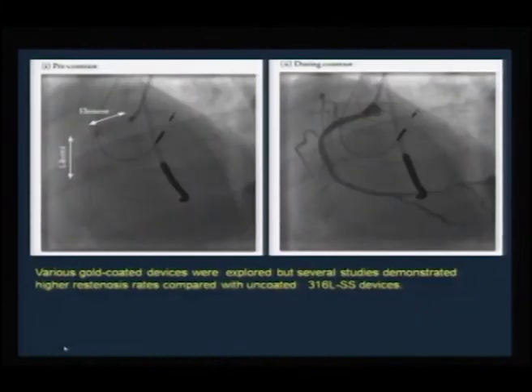Now, if you see here, the visibility is much better in the element stent because of the presence of platinum, whereas the Liberty stent is predominantly a stainless steel stent, and for a physician, he would rather go with element stent, mainly because without the dye he can easily map it. In other words, these are the X-ray images taken when the stent is deployed inside the heart. So, the visibility plays a very important role when you are looking at a proper alloy. Whether it is a 2 millimeter diameter or 4 millimeter diameter, we see proportionally the visibility is much more pronounced in platinum alloys.